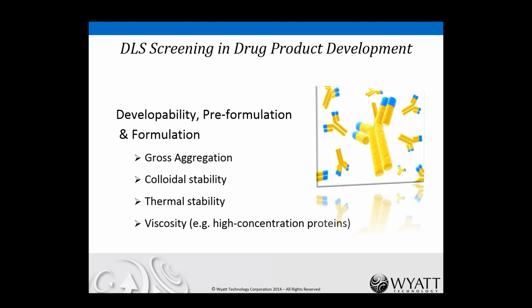So there are a few areas where dynamic light scattering really shines in drug product development, and those are the phases looking at developability of candidates after identifying several candidates for continued development, pre-formulation to identify, with minimum sample volume and maximum speed, ways to go forward in your studies with formulations that work well, and then in final formulation. The ways dynamic light scattering is used include assessing gross aggregation, so what aggregates are present, and as you'll see, in dynamic light scattering we're focusing on submicron aggregates. Looking at the propensity for aggregation through the colloidal stability and the conformational stability, usually in terms of thermal behavior. And finally, if you're working on high concentration proteins, dynamic light scattering is a great way for screening viscosity of highly concentrated protein formulations rapidly and with minimal sample volume.